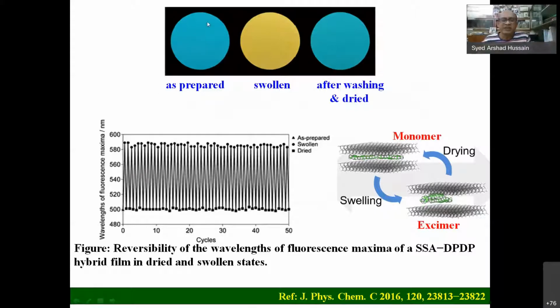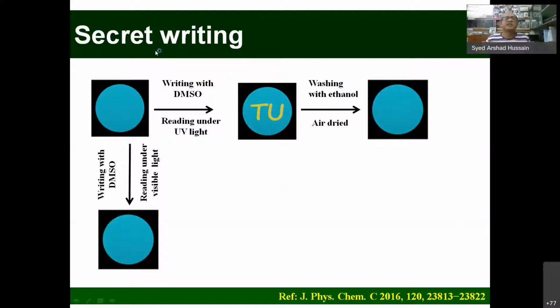So here I am showing this is as prepared, this is swollen. This is again after swelling; when we expose it to UV, you see the color change. Then again we wash the film to take out the DMSO. Again you see the original color come back, and then when dried, the original comes back, and it's a reversible process. And we checked it more than 50 times. We tried, and it's possible. It's shown schematically here. You see in dry condition single molecules are flat, but in swelling you see more than one molecule stacking. It's also independent of solvent. Even with water this is possible, but we use DMSO due to its high boiling point, so it remains for a longer time. So we propose this can be used for secret writing.